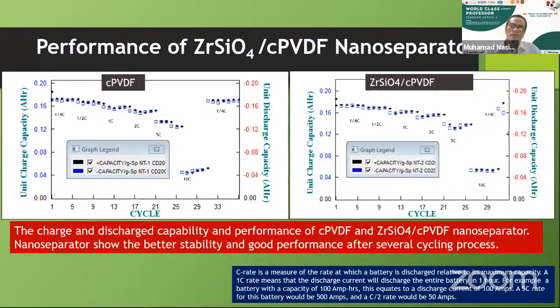So we do the C-rate test. We use from the low C-rate to the high C-rate. So you can see here, this is very stable. And the important point is after we use the high C-rate, and then we go back to the low C-rate, the performance is still the same. It means the stability of the separator is very good.